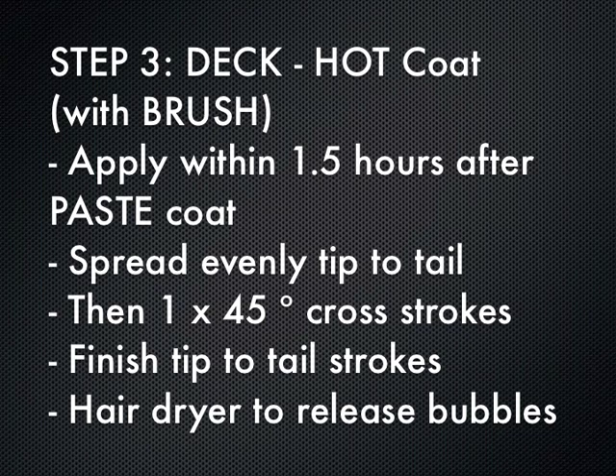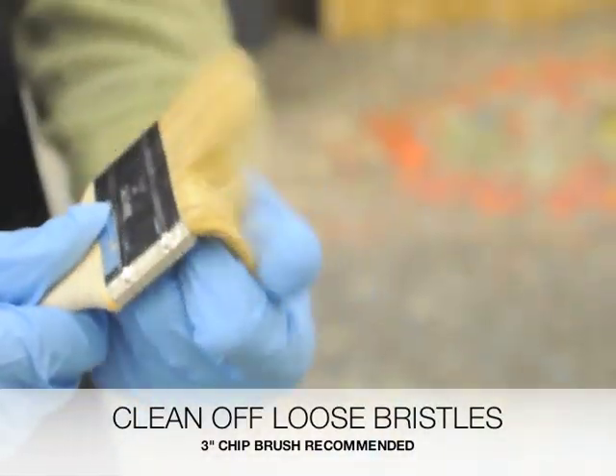Once the paste coat has gone tacky, you can apply your brushed hot coat. If the paste coat is allowed to fully cure, you'll have to sand it back with sandpaper to create a mechanical bond for the hot coat. Use a clean, dry brush and remove any loose bristles.